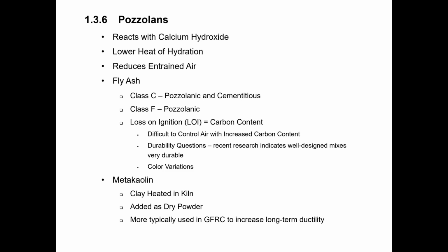One of the key material properties that we're interested in with regard to pozzolans is the loss on ignition. This is a test that can be conducted to determine the carbon content of the fly ash. Keep in mind that fly ash is a waste product. It results from the burning of coal. So depending on what type of coal is burned to get the fly ash, that will determine whether it's a Class C or a Class F ash. And then the loss on ignition test can be done to determine what the actual carbon content is of the fly ash. So the carbon content affects the air entrainment.